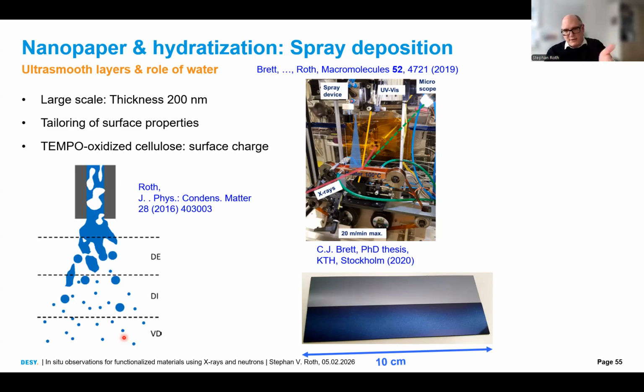And this is what we do here. And you see here already, this is cellulose nanofibrils, 200 nanometer thickness on a silicon wafer. This is a pure silicon wafer. And this here is the coated silicon wafer, blue color, around 200 nanometer. So it's 10 by 2 centimeters.